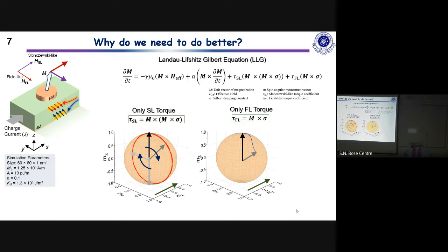If we do this calculation, then it is seen that these two types of torques do not cause a deterministic switching of the magnetization. The first type of torque, which is called the damping-like torque, only has a rotational motion of the magnetization. This has a rotational symmetry, which means that if you start from this top position, the magnetization will go on rotating along this plane as long as the current is applied. And the field-like torque produces a canting of the magnetization.